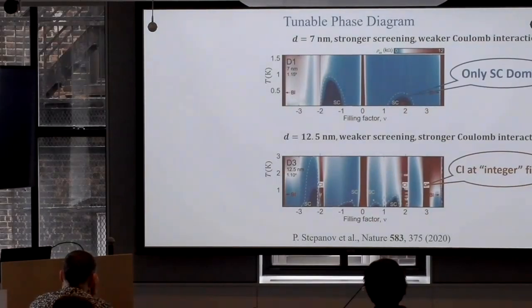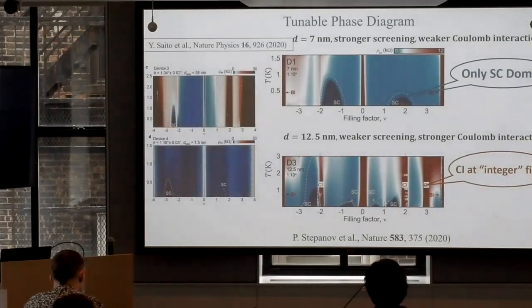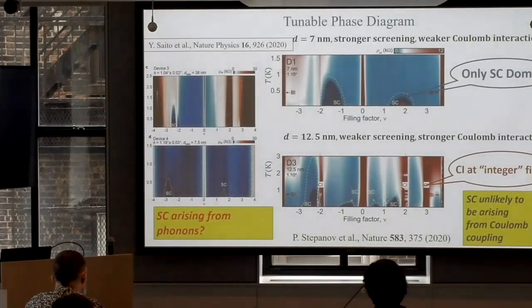Okay, so this is what I was telling you, I just gave you the punchline. So at 7 nanometer, stronger screening, only superconductivity survives, okay? And then when you go to 12.5 nanometer, weaker screening, correlated insulator phases come out, okay? So this is some evidence that it cannot be regular electron-electron. So these are the papers that I read from the abstract already.